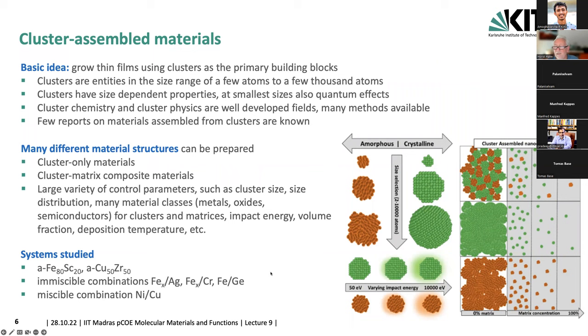So this would be, if we can stabilize that, which I will show you later, it would be something new, because whatever technique you use for nickel and copper, because they are fully miscible over the entire phase diagram or compositional range from 0 to 100%, you would create something which you could not make otherwise.